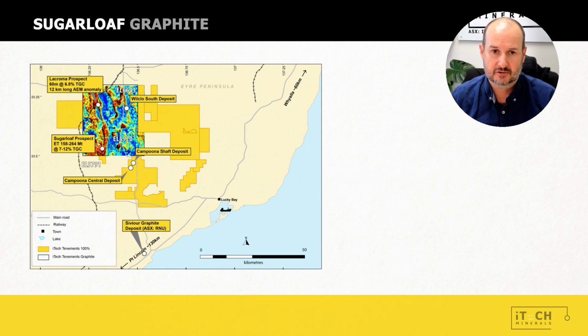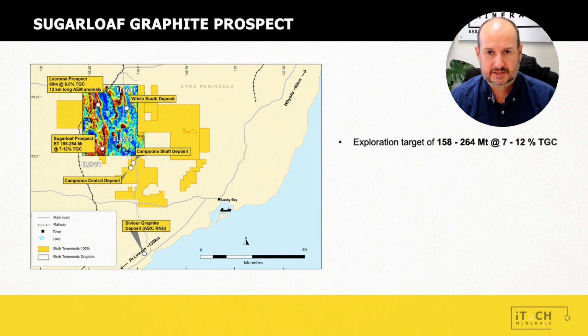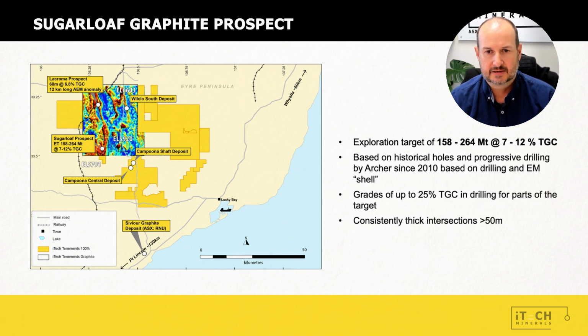So if we first take a look at our Sugarloaf project, that has an exploration target of 158 to 264 million tonnes at between 7 to 12% total graphitic carbon. Now, this is a well-constrained exploration target. It is based on about 33 historical holes that have been drilled through quite thick and high-grade intervals of carbon across that Sugarloaf project. And it consistently intersects intervals of greater than 50 metres.